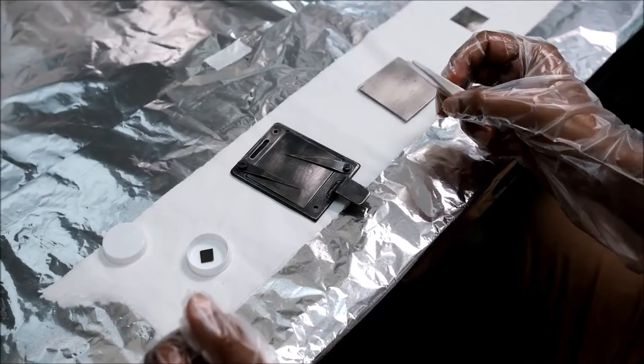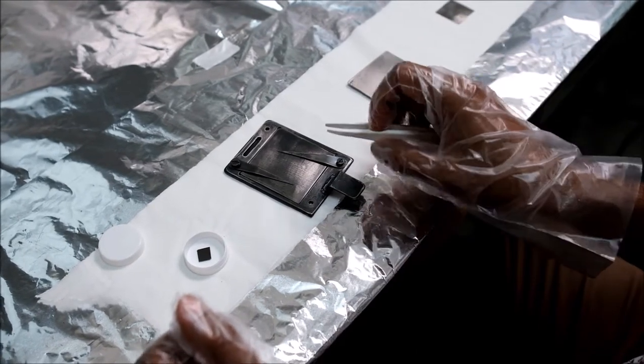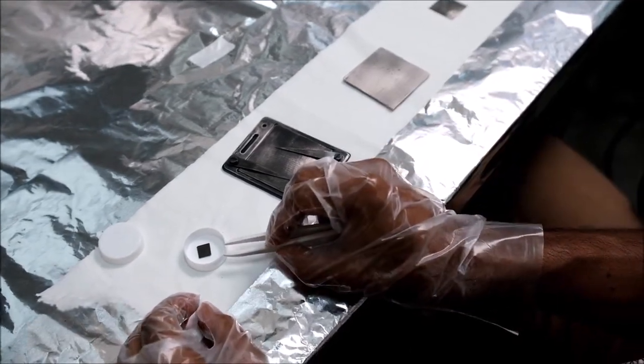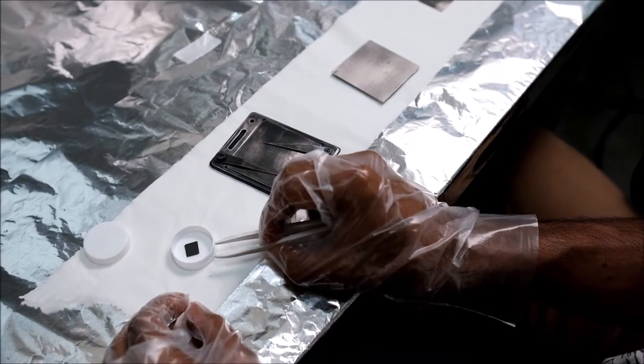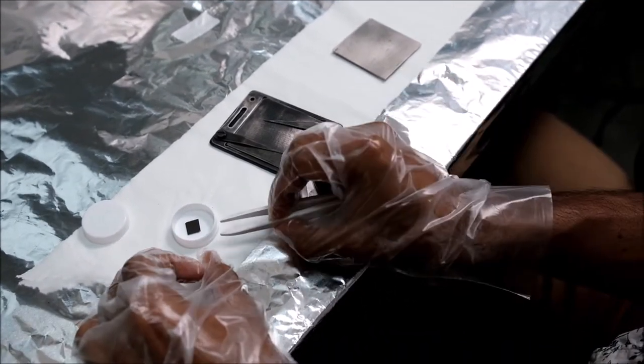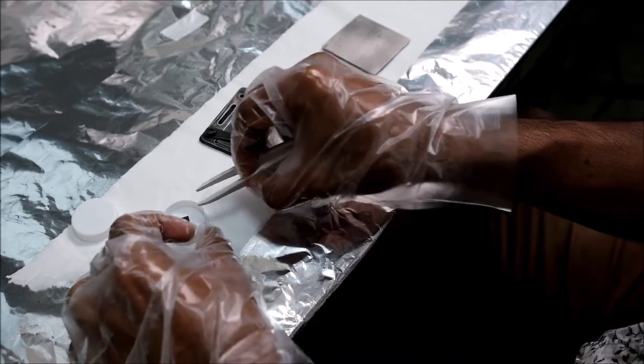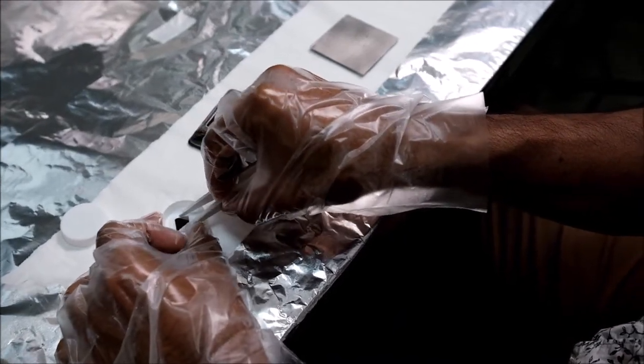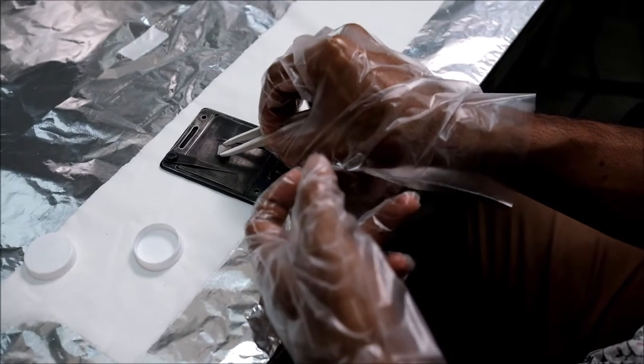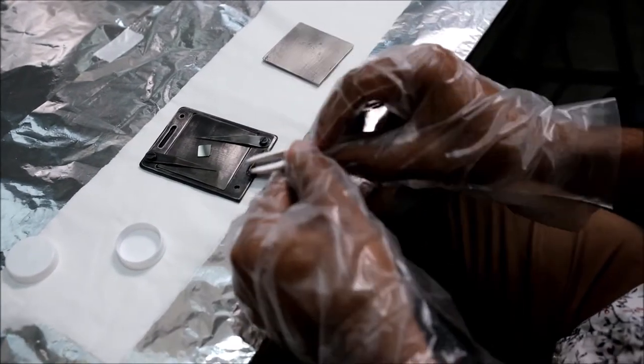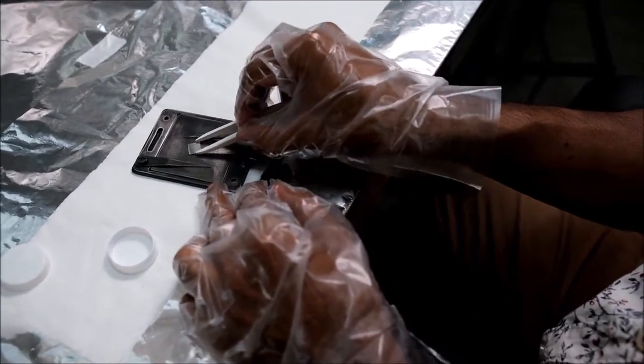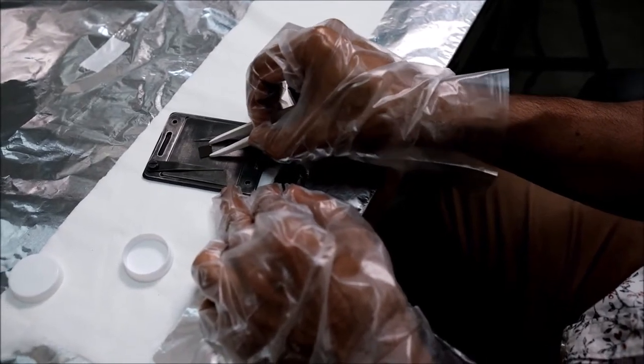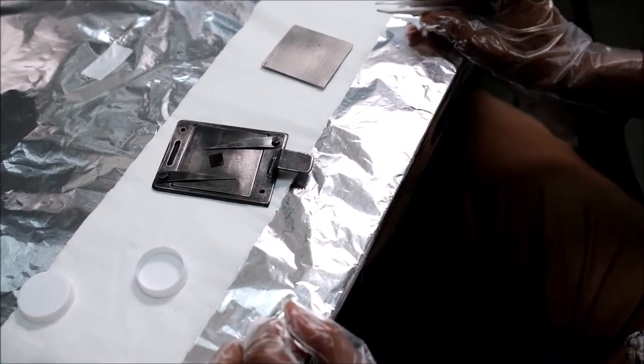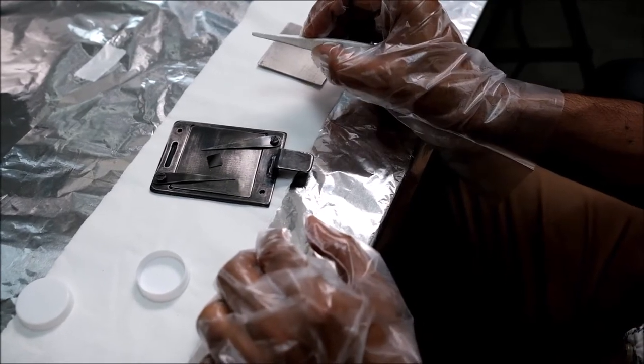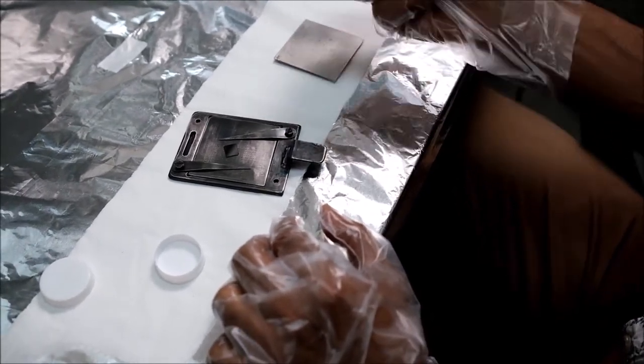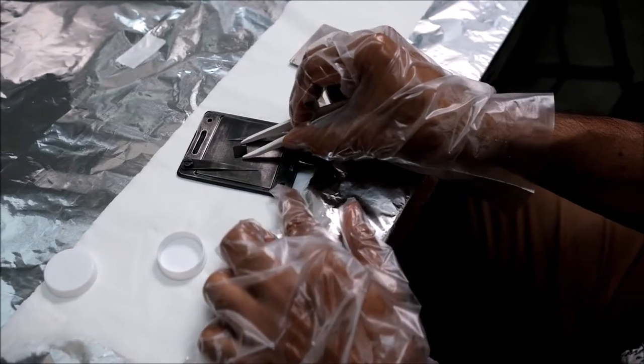Now I will show you how we attach the substrate onto the holder. So this is the clean substrate I kept here. This is a platinum coated silica substrate, and I will attach the substrate onto the holder. I can use a double sided tape at the bottom of the substrate to attach it. This works very well for room temperature deposition, but for high temperature deposition we need to use another method, like silver paste at the bottom of the substrate.